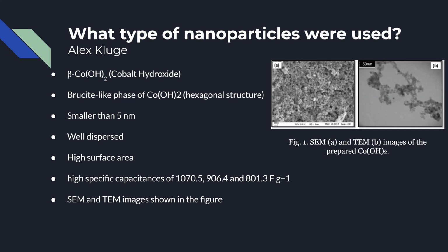They also showed high specific capacitances of 1070.5, 906.4, and 801.3 farads per gram at current densities of 1, 3, and 5 amperes per gram, which further shows their high energy storage abilities. And then finally, the transmission electron microscope and the scanning electron microscope images of the nanoparticles are shown on the right. The hexagonal structure and well dispersion can be seen through these images.